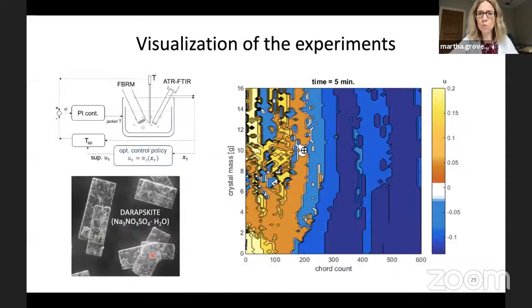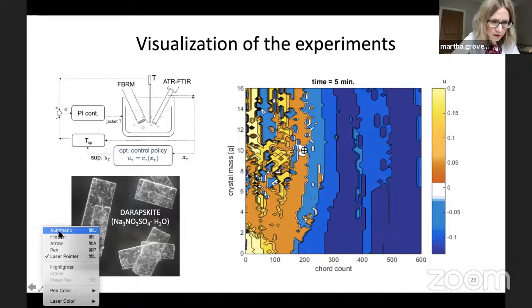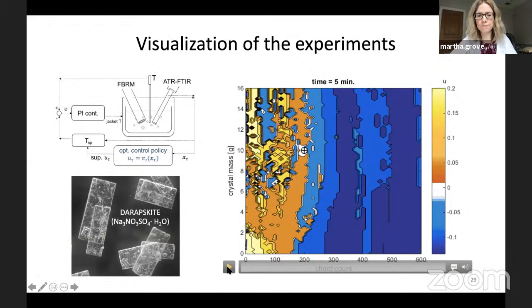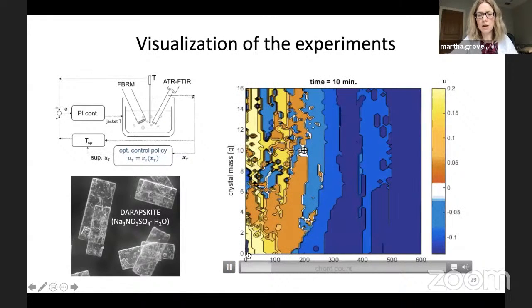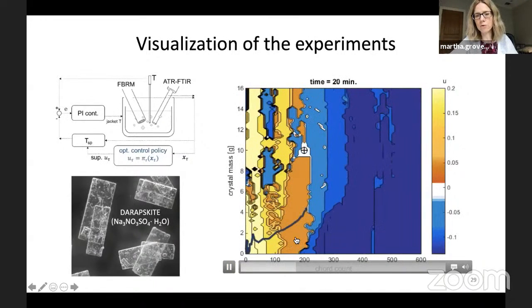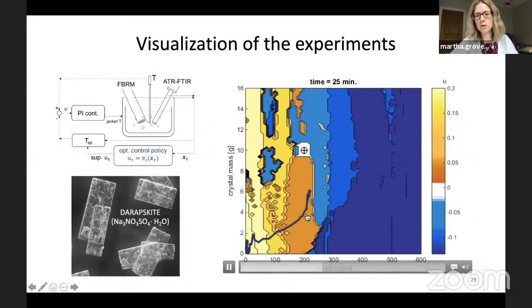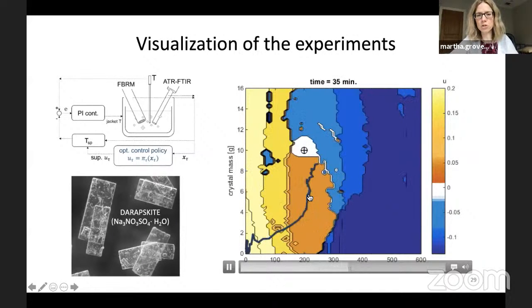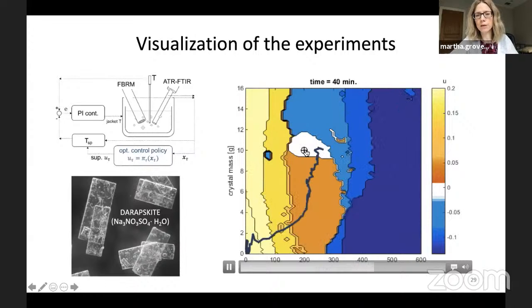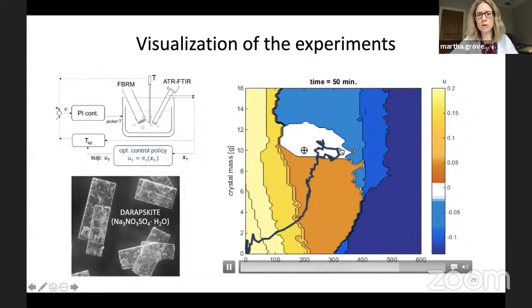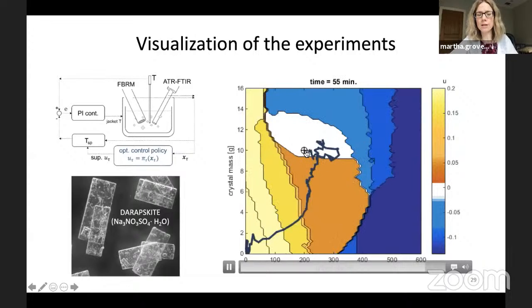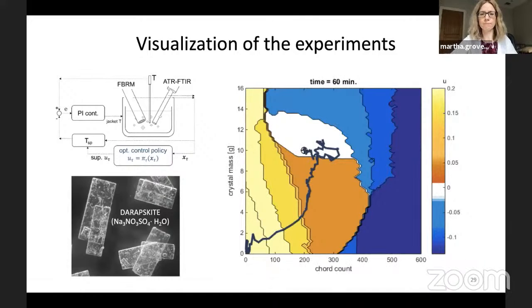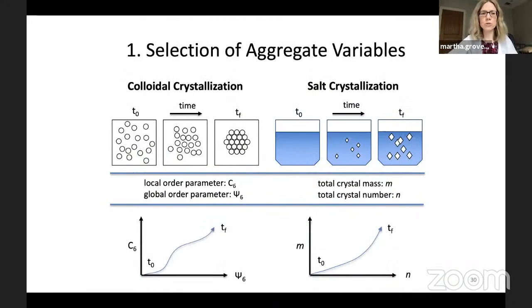And so now we're going to watch how the system evolves on the optimal policy, starting with no crystals. So let me go back, see if I can get my movie. Good. Okay, so we're going to start with no crystals. And so we have supersaturation then. So we're going to drive nucleation. Okay, so now the cord count goes up. We nucleate a lot of crystals. We back off on our supersaturation to try to achieve this target over here. We pass it a little bit. The system is stochastic, but we turn around and then we can come back here and park on top of our target.